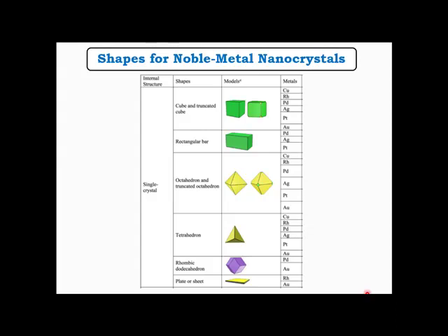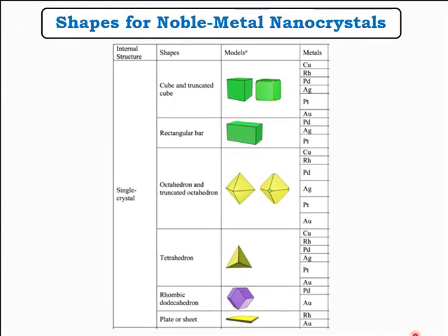It should be pointed out that the presence of a capping agent significantly affects the internal structure of the product, in addition to the surface structure. One compelling example can be found in the synthesis of palladium nanocrystals, that is, using noble metal nanocrystals. When a palladium precursor was reduced by ascorbic acid in a polyol system, single crystal palladium nanocrystals were found to be dominant in the final product.